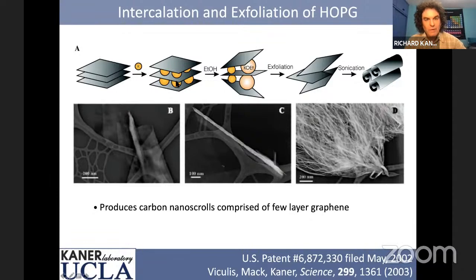So we did, and we hit it with alcohol, and the potassium goes to potassium hydroxide, the layers exfoliate, and when we sonicated, the layers scroll. Here's a lacey carbon TEM grid, and you can see the carbon nanoscroll, and it's so thin you can see the lacey carbon right through it. Here's a more tightly wound scroll, here's a whole lot of scrolls.